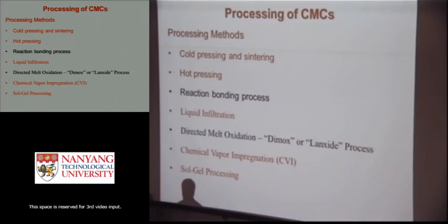For example, we take powders and mix them together, then apply high pressure and everything becomes a disc. If you do FTIR, we can use salt and mix your sample. You mix them, grind them together, then put them in a die, apply pressure, and you get a transparent salt window. So that one you can use for FTIR, right? If you know how to do FTIR, you should be able to understand what cold pressing is.